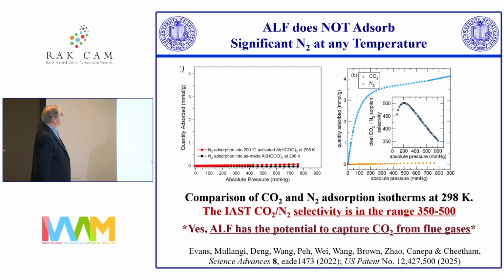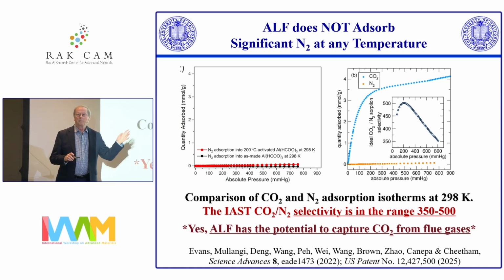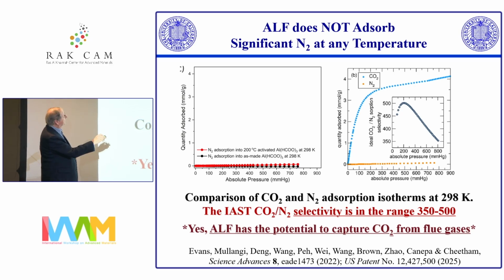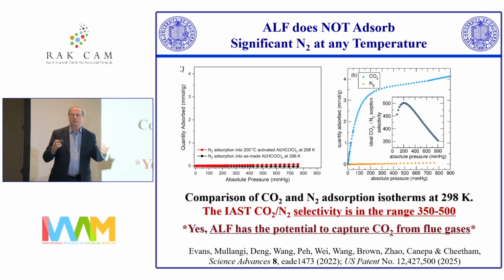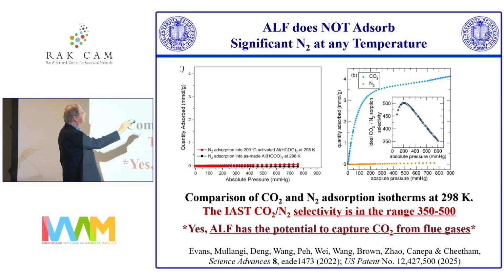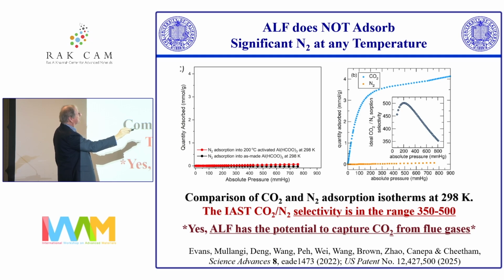And ours is no different, as I'll come to, but the surprising thing that we found was that ALF, and we call this material ALF, will not adsorb nitrogen at any temperature, which is kind of bizarre because nitrogen is awfully small. People use it to determine the pore size of their systems, and nitrogen just won't go in, even though CO2 goes in extremely effectively. So if you look over here, the blue line is the CO2 adsorption as a function of pressure. The orange line here is the nitrogen adsorption, which is negligible.